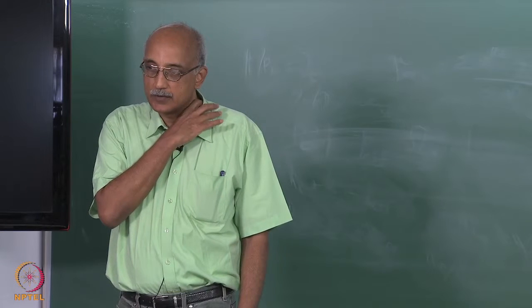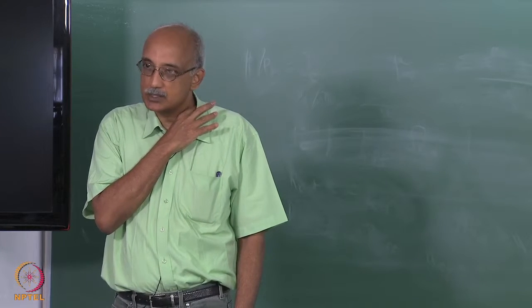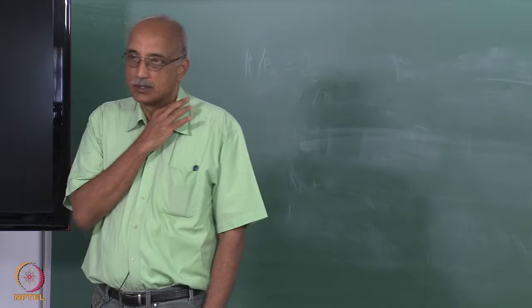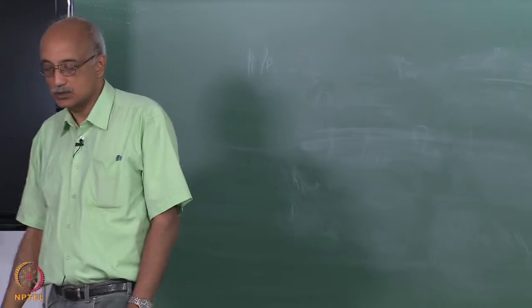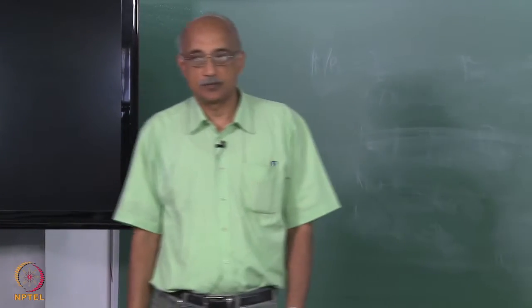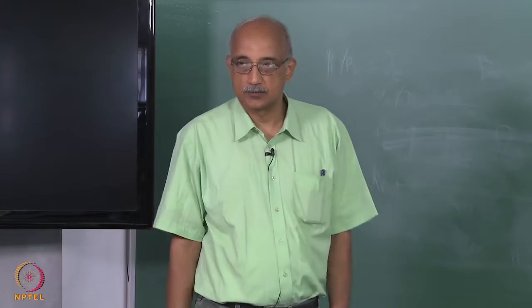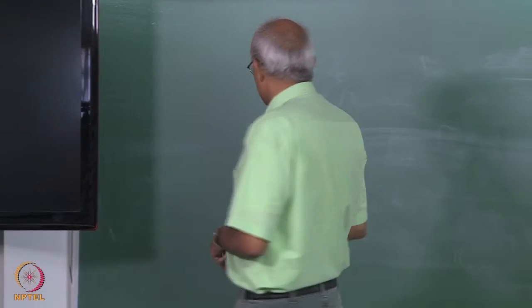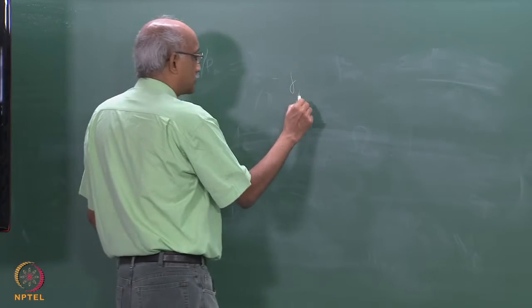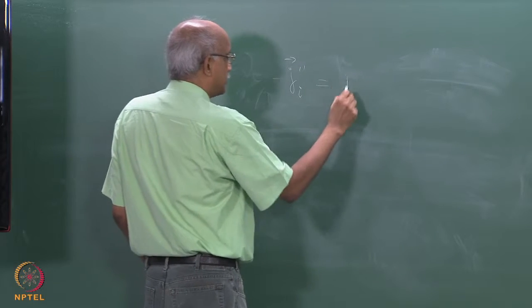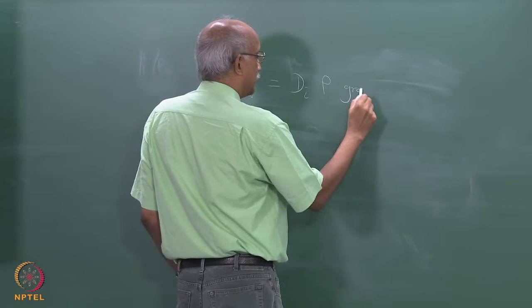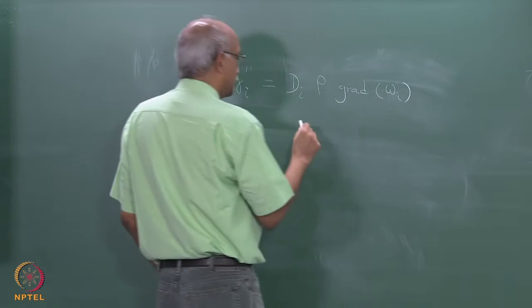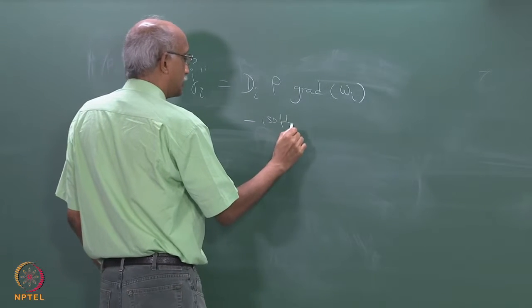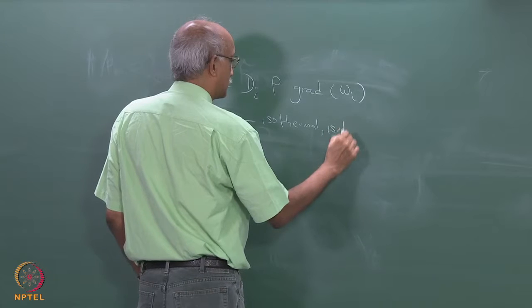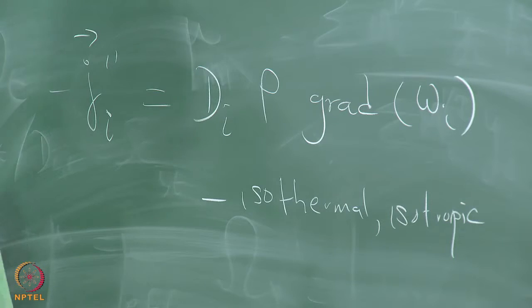But again, these are very important definitions. When we say isotropic, what it means is that the diffusivity is equal in every direction. And when we say isothermal, what we mean is there is no temperature gradient, which can also drive mass flux according to a phenomenon known as thermal diffusion. So, under these restrictive conditions, you can write the diffusive flux, minus j_i double prime, as equal to D_i rho gradient of omega_i. Again, this is for isothermal and isotropic conditions. And also there is an assumption here that it is a pure material, that it is not a mix